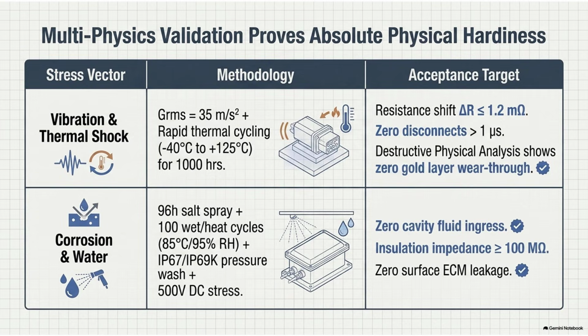And when the 1,000 hours are finally over and the unit is pulled from the chamber, the engineers don't just look at the data and say, okay, it passed, let's ship it. They perform DPA, destructive physical analysis. They cut the plug completely open. They take the connector that survived the test, cast it in solid epoxy resin, and use precision diamond saws or lasers to slice it directly in half. They polish the cross-section and put it right under a scanning electron microscope. To look for what?